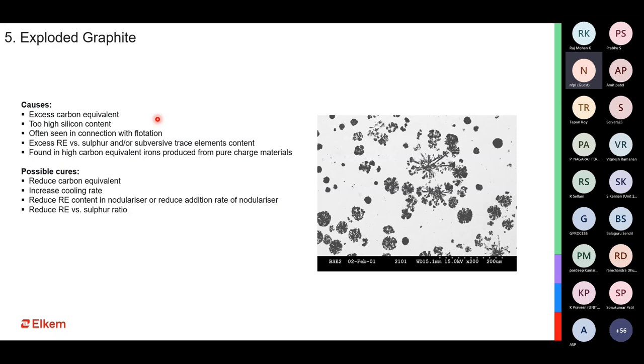How do you control it? We control it by reducing the carbon equivalent, by taking the carbon equivalent which is most suited to the particular casting geometry, and not go by a single carbon equivalent for all types of casting. So we have to modify and adjust our carbon equivalent for the kind of casting that we are manufacturing, not just going by the grade of the casting. We have to increase the rate of solidification, and we have to reduce the rare earth content in our nodulizer or reduce the addition rate.